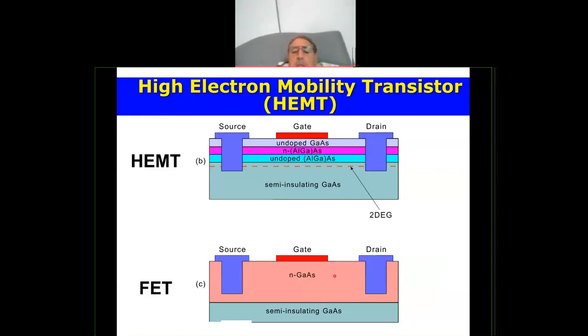So instead of doping the gallium arsenide, where we're going to have this transport of electrons, they actually dope the aluminum gallium arsenide, which has got a high energy gap, with silicon. But you create, of course, here now silicon plus atoms, positive charge, and electrons. But electrons, they never like to stay in a high energy state. So what they do, they go to gallium arsenide. So they move to gallium arsenide because it's a low energy medium. So what has happened, you left the silicon atoms here, positively charged, and you move the electrons here, which is going to be moving into a medium which has got no impurities, or very minimum number of impurities.